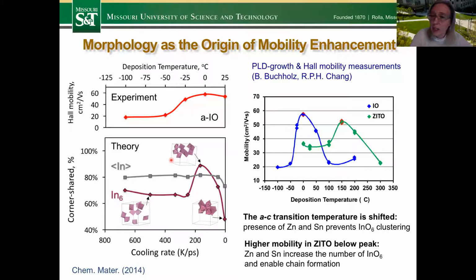We can take that step further and actually predict what will happen to different materials. So here I'm showing again experimental results for indium oxide. Again, that same mobility peak, just on the onset of the crystallization, we have the peak, and the same happens in zinc indium tin oxide. The peak is shifted, and the mobility doesn't go as low below this peak.